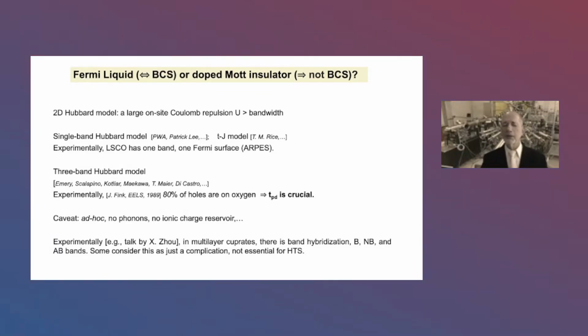It ignores phonons, it ignores the ionic charge reservoir. When you allow it to be doped, it is not even thermodynamically viable. As you add more and more charges, if you make the system infinite, the energy will go to infinity. And then we have this issue of multilayer cuprates, where certainly there are more bands. They are coming from different layers.